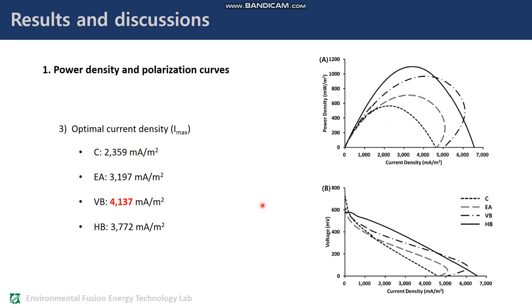The brush anode cells exhibited higher performance than the carbon cloth cells. The brush anodes showed 41 to 72% higher maximum power densities, 18 to 75% higher maximum current density, and 24 to 32% higher optimum current densities than the carbon cloth anodes.